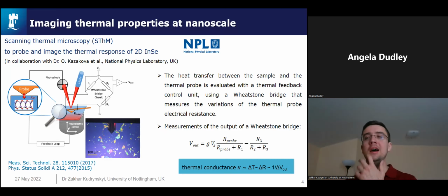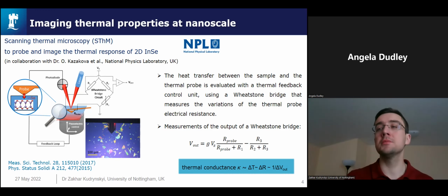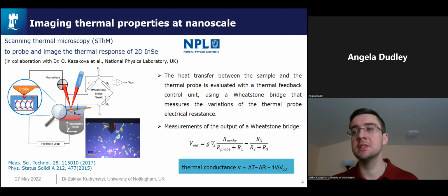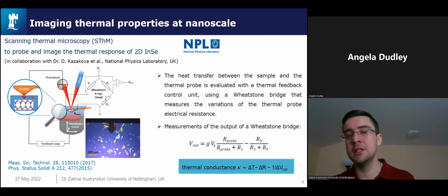So importantly to know from all that is that our thermal conductance is inversely proportional to the change of output voltage on the bridge. And an optical image here shows exfoliated nanoflakes of indium selenide on a substrate, and this is the SThM tip with a probe.